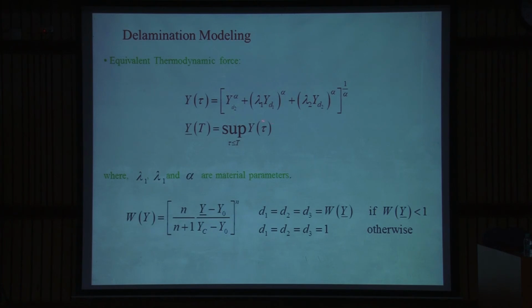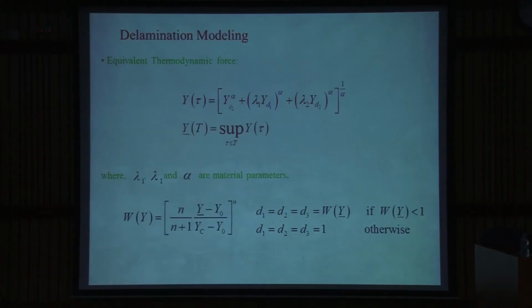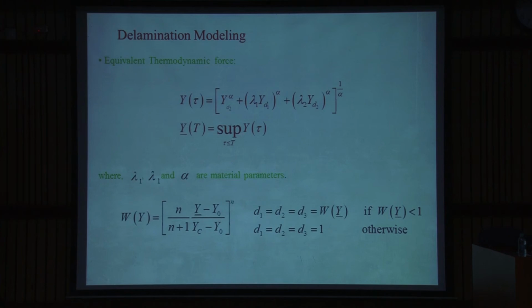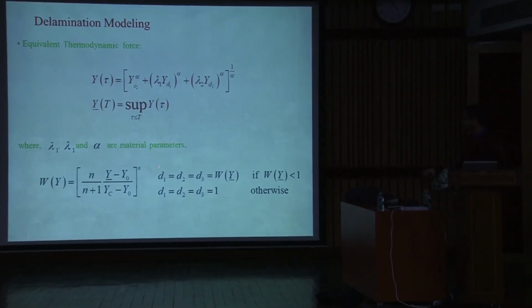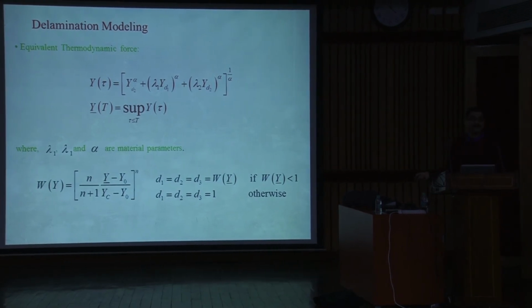One more thing defined here is that the crack will propagate only when the thermodynamic force in the next step is greater than the thermodynamic force that you had in the previous step. Based on the behavior of the matrix material, whether it is brittle or ductile, you can do one more fitting based on the indicator N, and get the corresponding damage indicators. In this case, instead of having a separate indicator for each mode, only one indicator has been used. That means the failure in the 3 modes will happen simultaneously, or together.